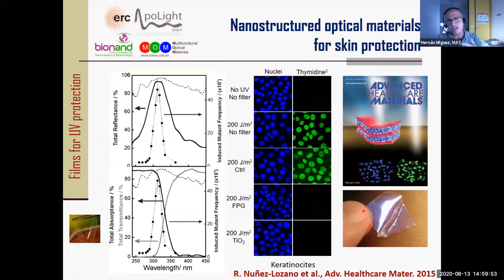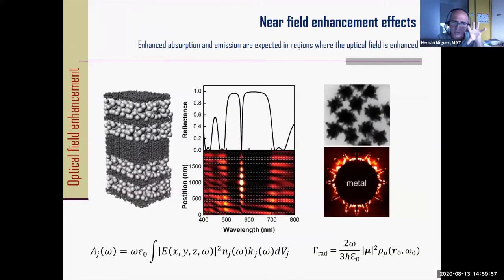But there are many other interesting things that happen in these materials. But if you get closer, let's see, we could see inside. So this is a simulation, what you're looking at here, of how the optical field intensity, how light intensity is distributed inside one of these materials. So just by playing around with the thicknesses of one of these multi-layers, as you can see here, you can obtain the following results at certain positions that are well defined, right?